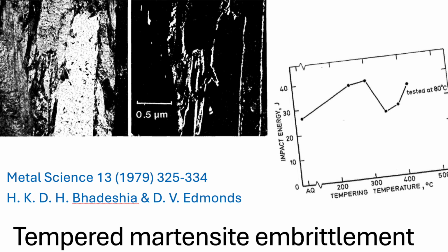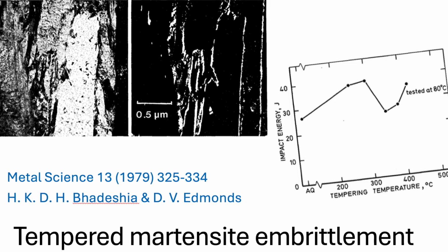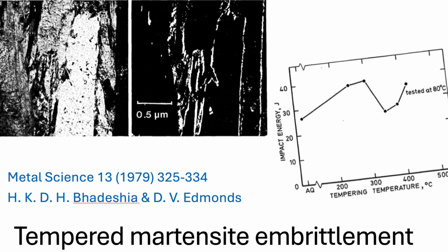But here, the decomposition product, this cementite, forms these incredibly small, discrete, almost continuous films right along those boundaries between the martensite laths. Ah, so like thin sheets. Exactly. And these thin, brittle sheets act like pre-existing microcracks. They're just sitting there waiting for a stress to exploit them. They provide an easy path for fracture. So just to recap the chain reaction for this specific steel, the unstable retained austenite is the chemical trigger.